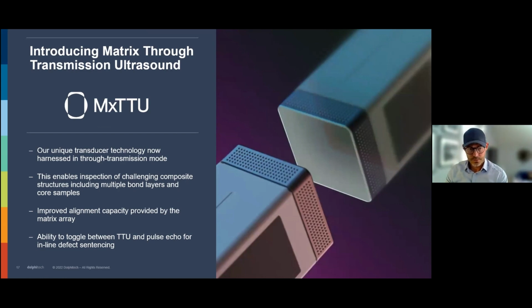Through transmission ultrasound is quite easy to use. As you can see here, that's when you put two transducers next to each other. And this is easy because you have a footprint that is about 32 by 32 millimeters. And to find this on each side of a composite is easier than a probe, right? With a probe, you have one little signal and you have to look at a single element probe. You have to look for that A-scan and see if the A-scan is big enough and say, okay, we're aligned. And then you move along.